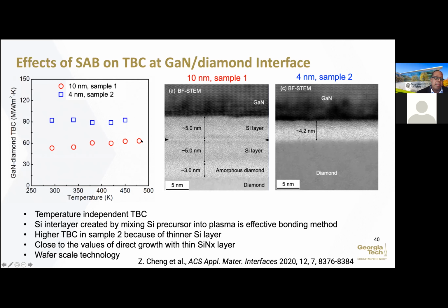Remember, before I said some of the best was between 80 to 100. And so now when I do this thermally activated bond, this plasma activated bonding, I'm sitting here around 90. So I'm right in that sweet spot of having some of the best thermal interfaces that's been reported. And there's still a lot of room to grow in terms of dialing in these process parameters to control the amorphous layers. In this case, we're not annealing it in order to get rid of this amorphous layer. So there's quite a bit that we can still try to do in order to use plasma activated bonding in order to produce extremely low thermal interface resistance combinations of heterogeneous materials.